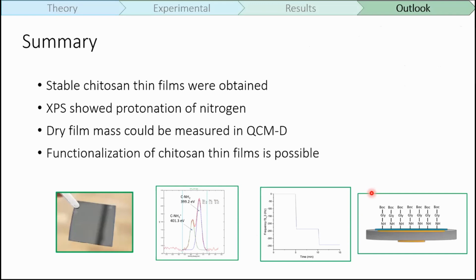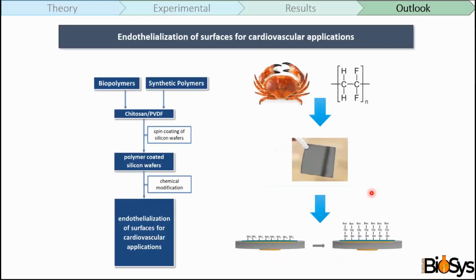In summary, all in all, we were able to produce stable chitosan films. With the XPS measurements, we can show that our film can be protonated, and with neutralization then deprotonated. We can successfully measure the dry mass of our films inside QCM. And the functionalization of the chitosan films is also possible.